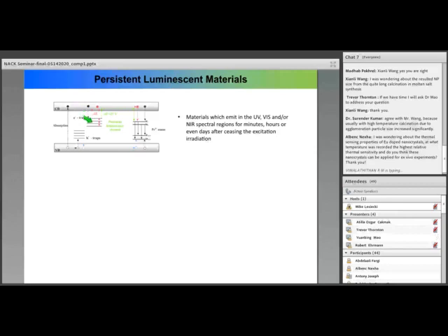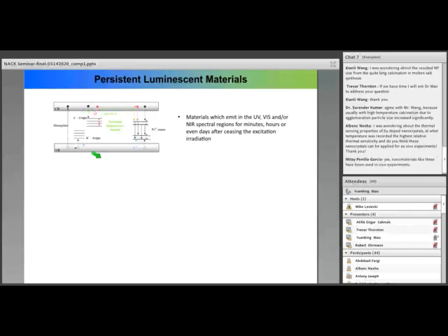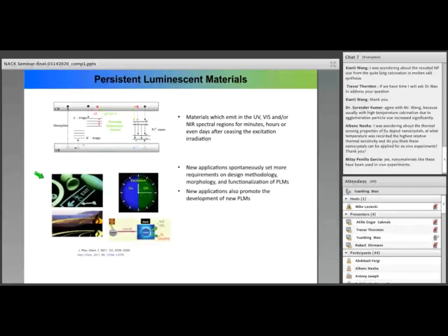They store the energy, and when the irradiation source is removed, the electrons at the traps get back to the band structure or are directly transferred to the activator centers. That process needs only thermal vibration, which is enough. That's how persistent luminescence works.